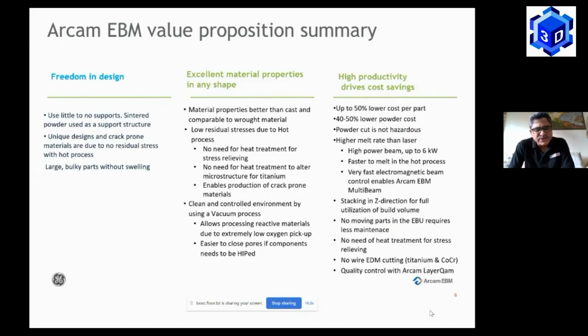In such a process, since the entire build platform is already at a high temperature level, those sintered powders act as a support. Therefore, we require very little support when we build a component. It serves as powder. Apart from that, the environment is already high temperature and we have a vacuum environment. Therefore, the process helps us to build crack-prone materials, typically titanium alloys and some of the nickel alloys, which are extremely difficult from a metallurgical point of view when we do the melting process.